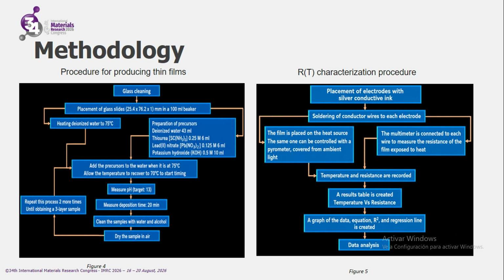RT characterization procedure. Placement of electrodes with silver conductive ink. Soldering a conductor wire to each electrode. The film is placed on the heat source, whose temperature can be controlled and measured with a pyrometer. The multimeter is connected to each wire to measure the resistance of the film exposed to heat. Temperature and resistance are recorded. A results table is created, temperature versus resistance. A graph of the data, the equation, R squared, and a regression line are created for data analysis.